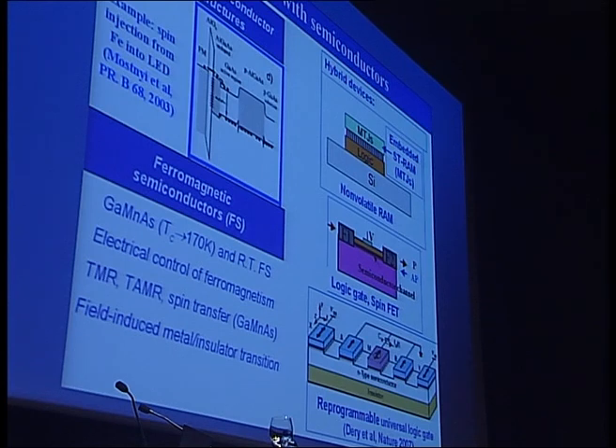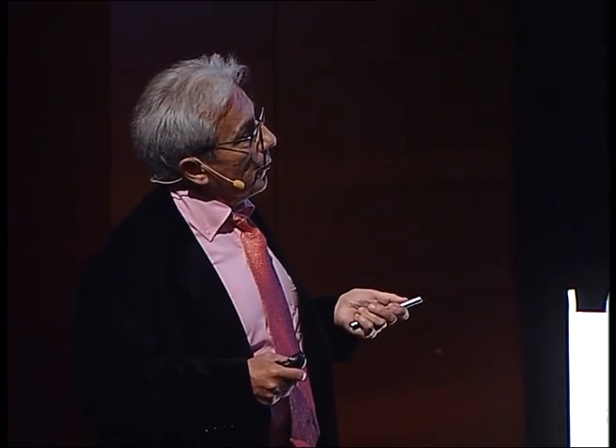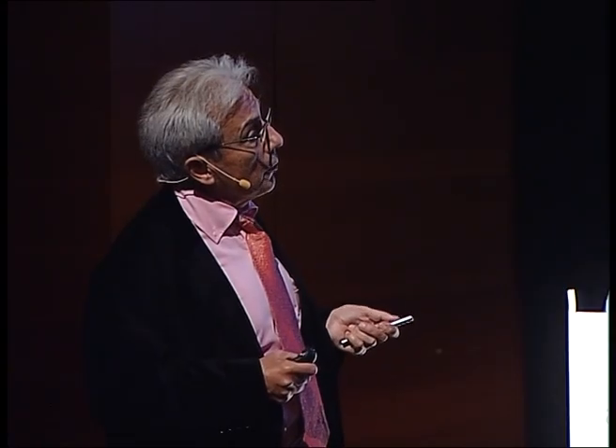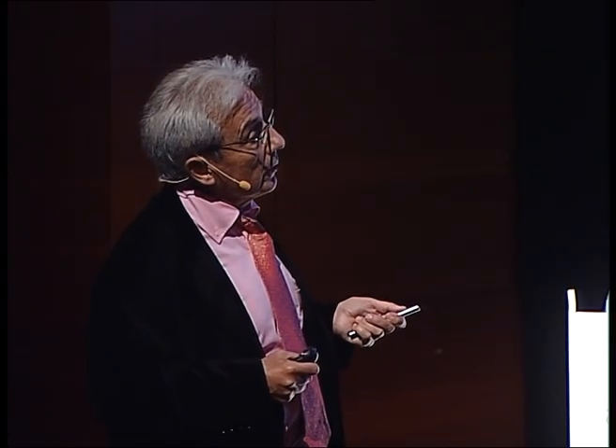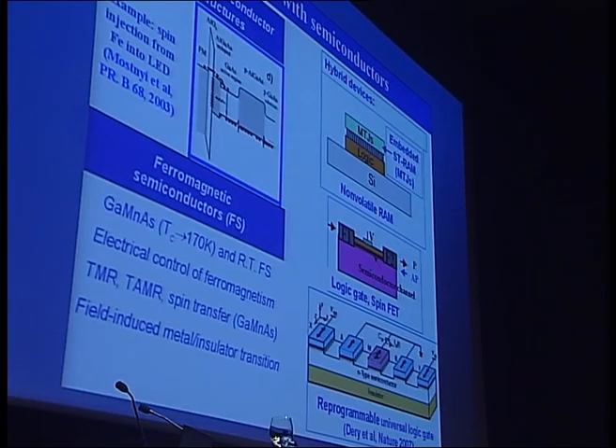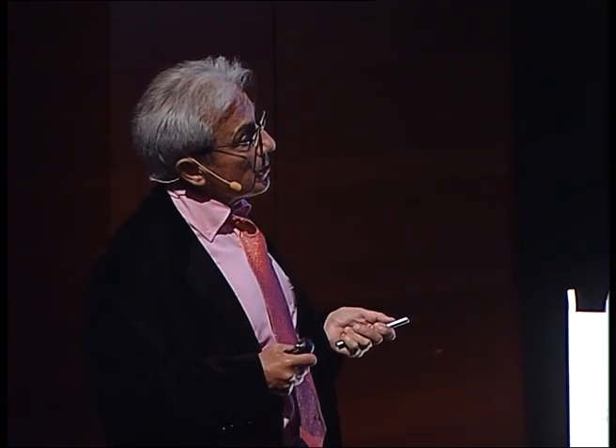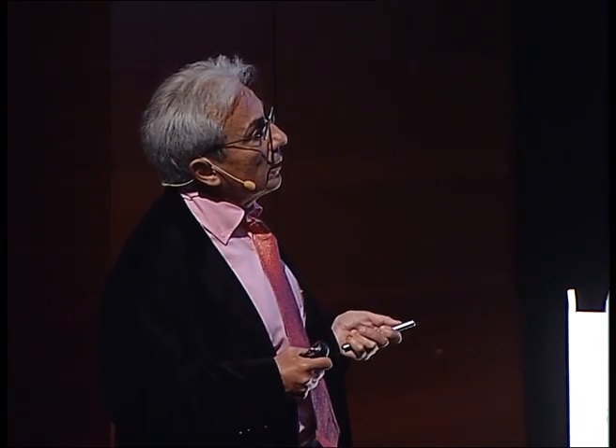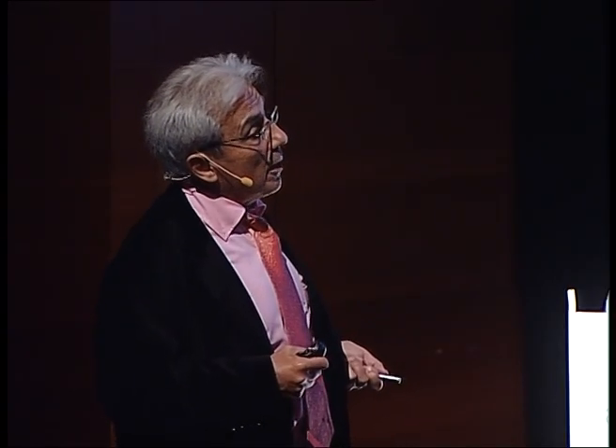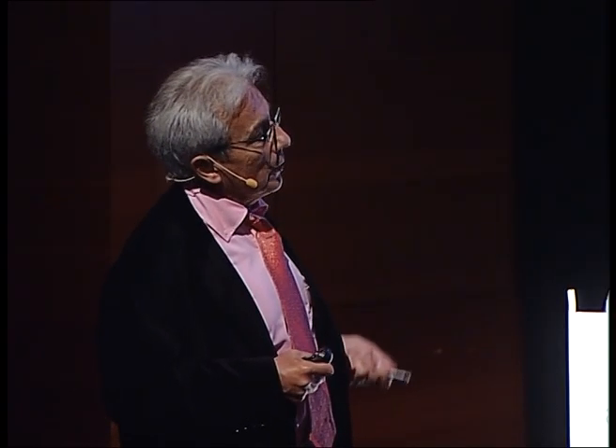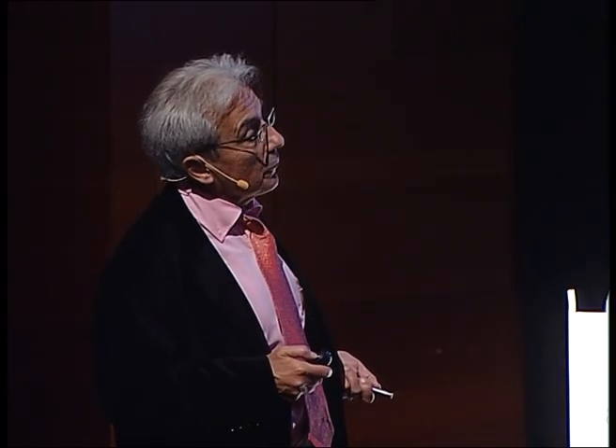In fact, there are several difficulties on this way. In this sort of structure, what one needs is that the spin of the electron is conserved, does not flip during its stay in the channel. One needs that the dwell time of the electron must be shorter than the spin lifetime, and this is relatively difficult to obtain with semiconductors. The velocity of the electron is small. Generally, there is a strong interface resistance, so the electron is not transmitted directly. There are several rebounds. The dwell time is generally too long to obtain good properties of this type of device.